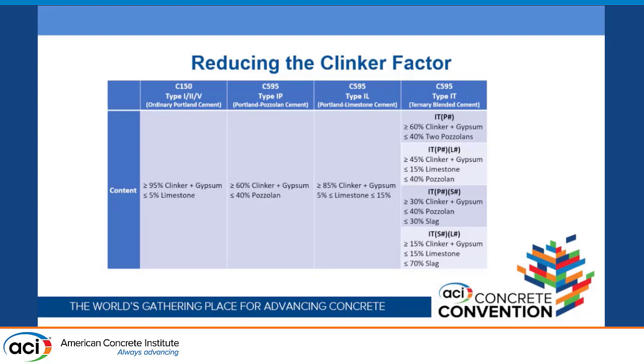So this here is just a focus on reducing the clinker factor. This is just a table. As you can see here, Type 1/2/5, 1P, 1L, 1T. So 5% max limestone, you're still going to need about 95% clinker, the Type 1/2/5 ASTM C150. And then when you get into the C595 cements, the 1L allows you a minimum of 5, maximum of 15% limestone. And the 1Ps, you can reduce your clinker factor all the way down to 60.